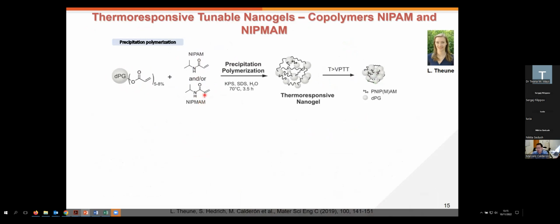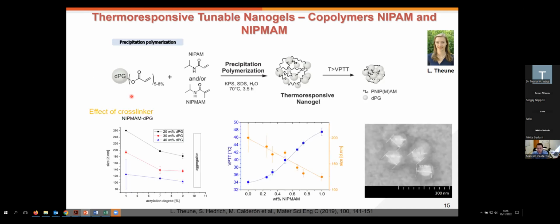That is a very analogous monomer that has a transition temperature around 48 degrees. And then by playing with the conditions of the polymerization, concentrations, the concentration of surfactant, use or not of catalyst, etc., we could control the properties of our nanogels. Some examples of the properties we could control: on one side, we can control the sizes by changing the acrylation degree of the cross-linker. And we can also change, for instance, the transition temperature and the sizes when we change the ratio between the copolymers, or the comonomers, that we use.